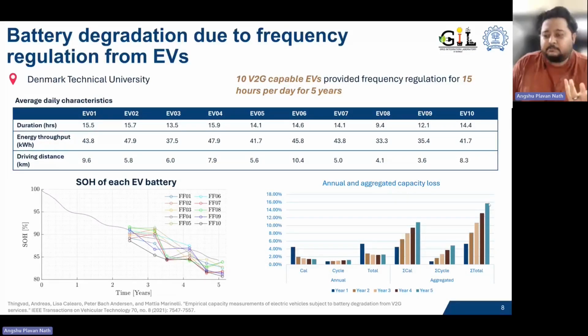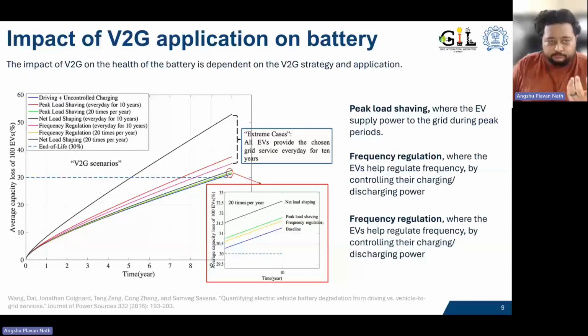But of this 16%, around 10 to 11% was contributed due to calendar aging, and not because of cycle aging. So again, it shows that the calendar aging is dominant in here as well. So irrespective of whether the vehicle was being used for V2G or not, this calendar aging would have been there. So due to vehicle to grid, a small percent of the cycle aging has added on top of it. But again, the calendar aging is dominant in this as well.